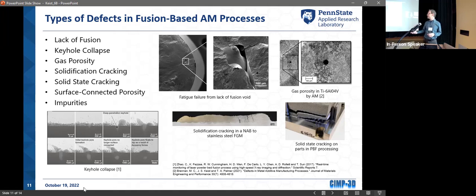If you get impurities, like anything on the metal powder or the metal wire, things like oil and grease, that is going to burn up and cause a gas pore. And there's an example of a gas pore here. Finally, we can get some solidification cracking. Certain alloys do not want to be melted, or they do melt. They can form cracking during solidification as metal tends to shrink. And therefore, if you don't have enough metal to fill in those shrinking areas or voids, you can end up with some cracks like this.